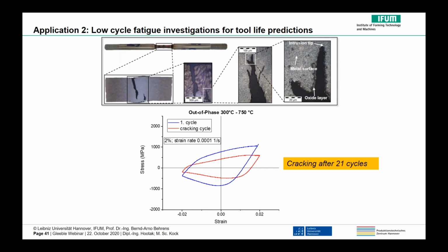For the specimen treated by the OP TMF loads, oxidation occurs in the hot work steel. The pictures illustrate the representative surface oxide and oxide intrusions. During the thermomechanical loading, the first oxide layer cracks so that the exposed metal surfaces oxidize again. It is typical of OP cases that an oxidation damage mechanism dominates, where the maximum temperature acts on the material concurrently to compression stresses, since void growth and intergranular cracking mechanisms are suppressed in compression. Here, cracking occurred after 21 cycles.